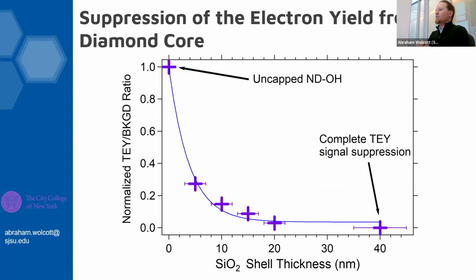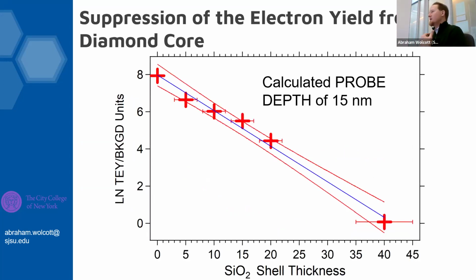And we can go ahead and look at our TEY data, the amount of electrons coming from our sample. We end up just looking at the ratio, and then we can plot that as a function of SiO2 thickness, take natural log, and end up getting an approximation of the probe depth that we can see into the diamond through our silica chemistry in this overlayer of the core shell. And it's about 15 nanometers into the sample.